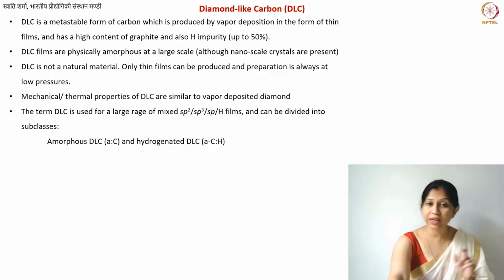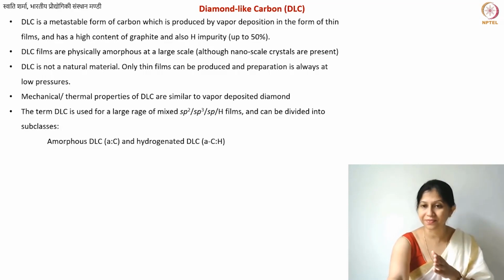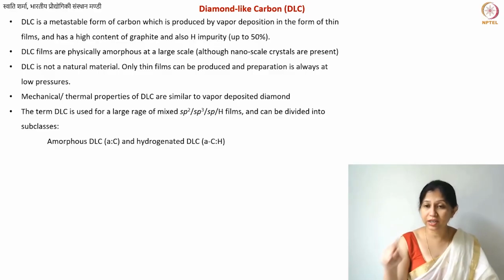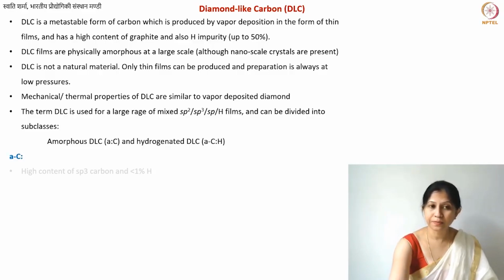You know that hydrogen is present in all cases in DLC, but it depends upon what the fraction of it is. The atomic fraction of hydrogen can be between 1% up to 50%. Depending upon the fraction of hydrogen, you call it either just amorphous DLC or hydrogenated DLC, sometimes also called amorphous hydrogenated DLC. So you write it like this, a-C:H. Okay, so let us talk about the amorphous DLC first.